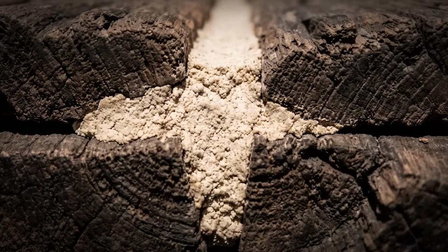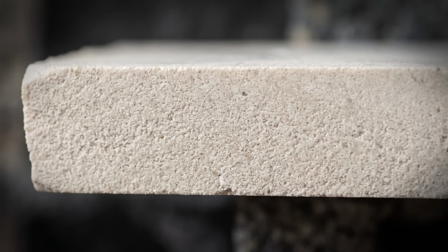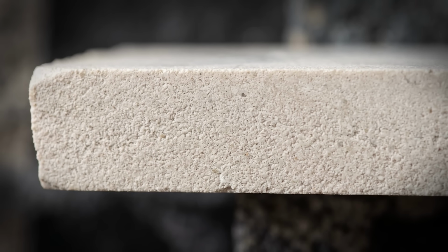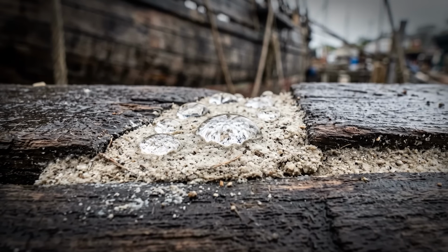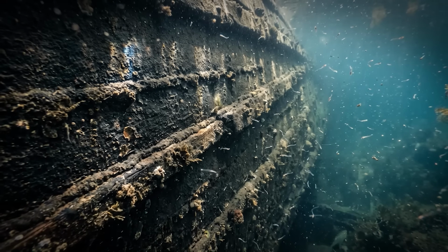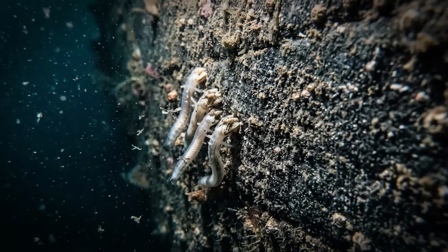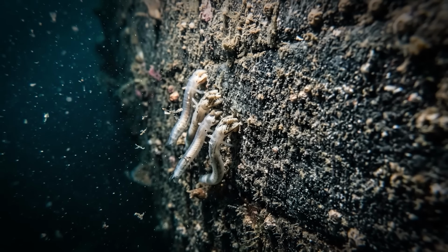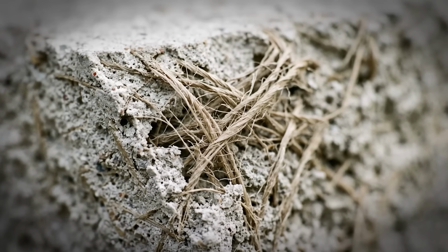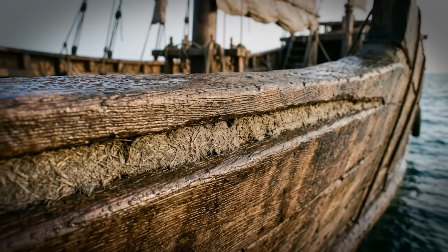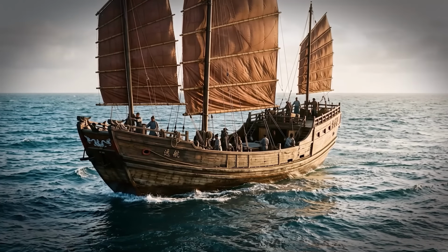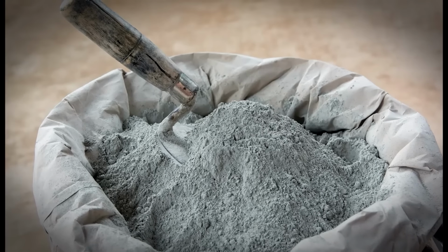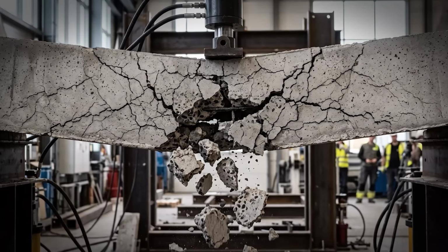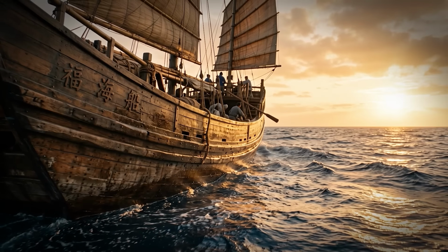Here is the part worth sitting with. Modern scanning electron microscopy of that same centuries-old Chunam reveals a microstructure with extremely few large pores, a dense, tightly bonded matrix with very limited pathways for water ingress. Water penetration is drastically reduced and shipworm larvae find little exposed timber to colonize. The calcified, oil-hardened surface is simply too dense, too chemically foreign, and too mineral-rich for teredo navalis to attack easily, and yet the material is elastic. The interwoven jute fibers and the polymerized oil allow the hardened compound to flex dynamically with the hull as it pitches through ocean swells. Modern Portland cement, the material we use to build everything, would shatter under those same stresses. The ancient compound flexes. It gives, but it does not break.